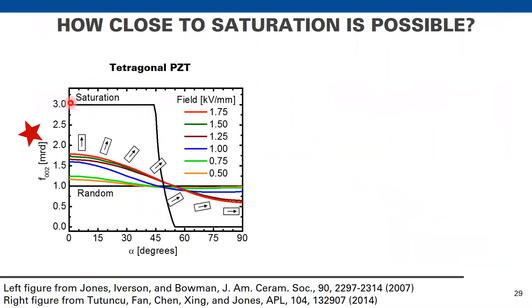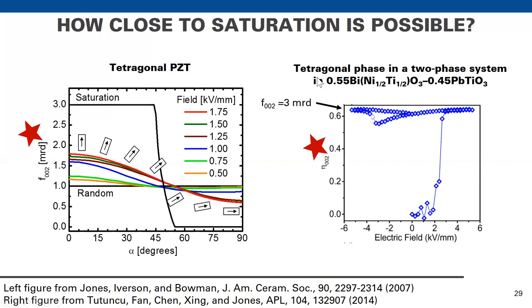So now we know that we have a saturated case, okay? And now we know that we have real domain textures in different types of materials. And so a natural question is, how close to saturation is possible? And I would say, based on experience for most single phase polycrystalline materials, it's difficult to get up here to values of 2 or 2.5. But we have seen in many cases in mixed phase systems where two polymorphic phases coexist that you can have a significant amount of domain reorientation. And that example is shown here for bismuth nickel titanate, lead titanate.